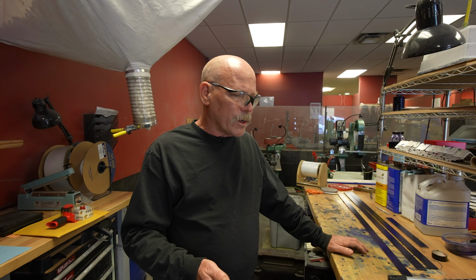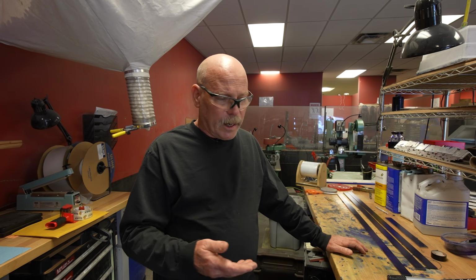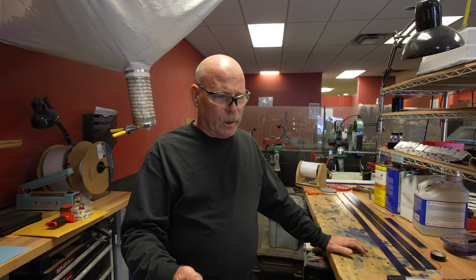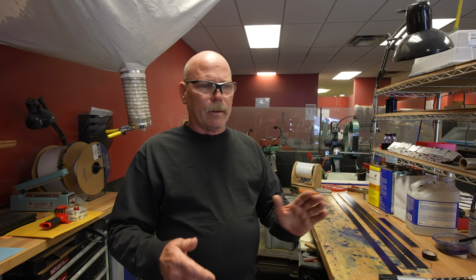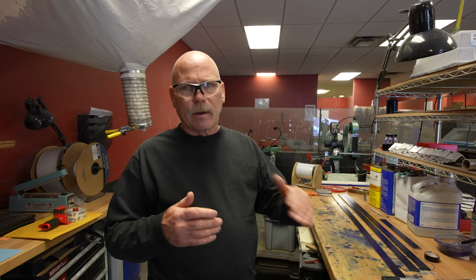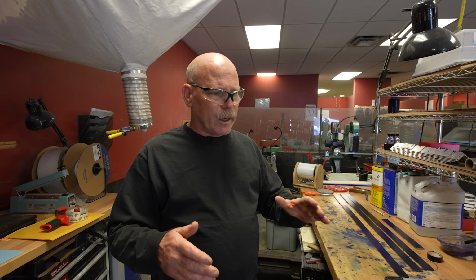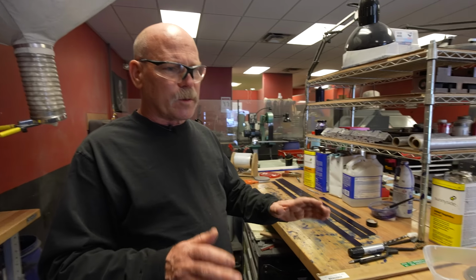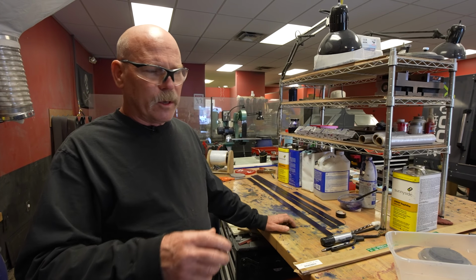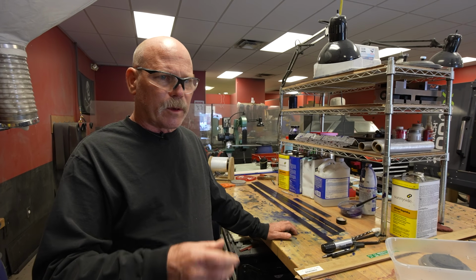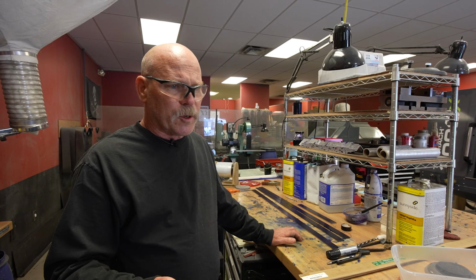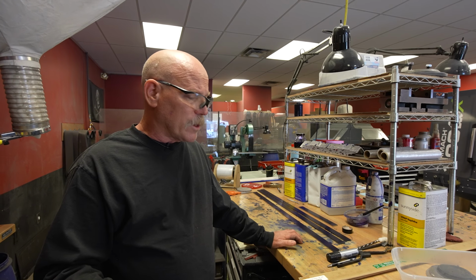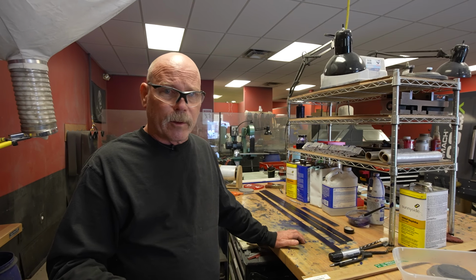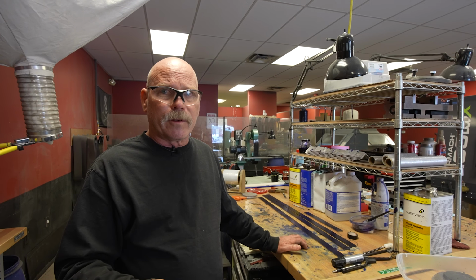With a hard chrome finish, we get an excellent quality finish, because our roughest finish we're grinding down to 30 microns, and then bead blast and then hard chrome. So we end up with a really, really nice, smooth, consistent finish. You can see the temper line in our blades because they're all selectively tempered. It's super, super durable and very, very corrosion resistant, which is one of the many reasons that I won the contest for the Navy SEAL knife in 1992.